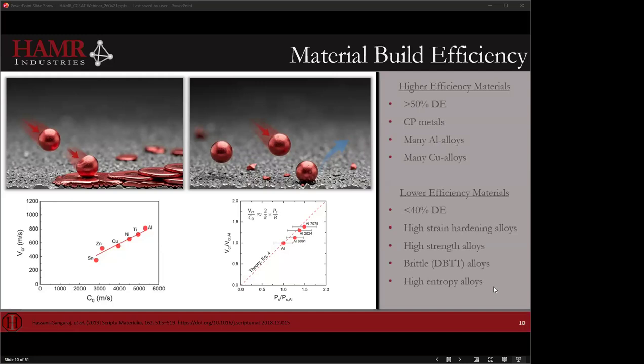The takeaway, though, is that these higher efficiency materials tend to be commercially pure metals. They have relatively achievable critical velocities. And then a lot of aluminum alloys and a lot of copper alloys. So generally speaking, softer alloys. Lower efficiency materials, where we're thinking less than 40% DE.